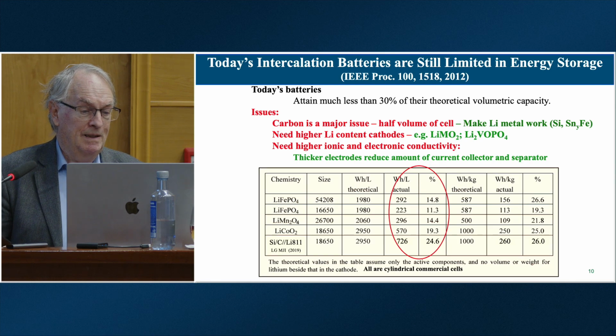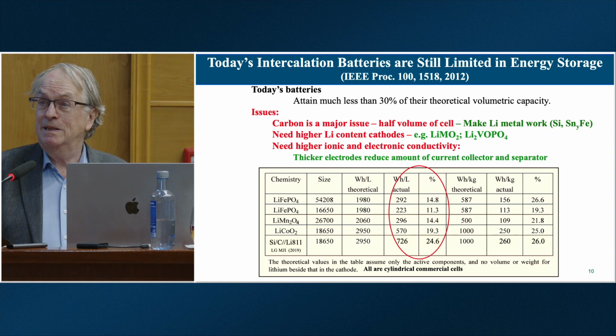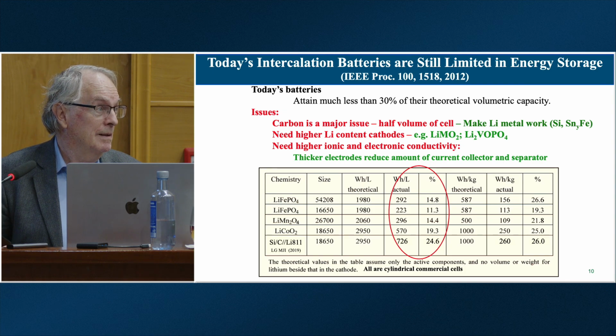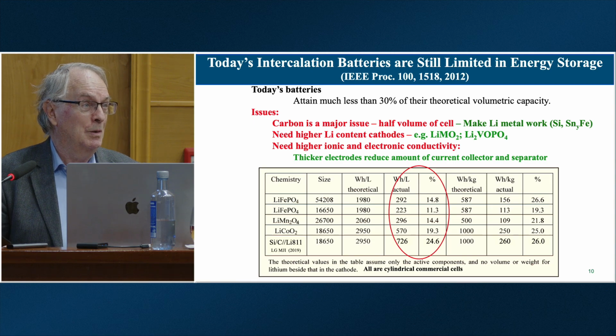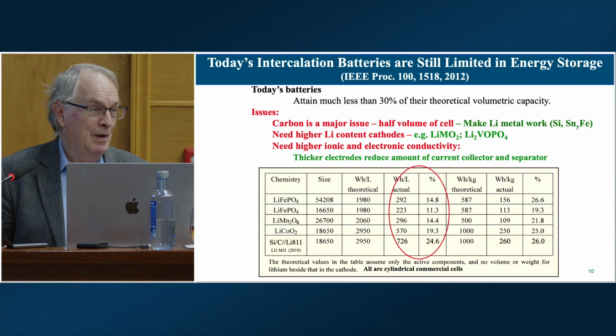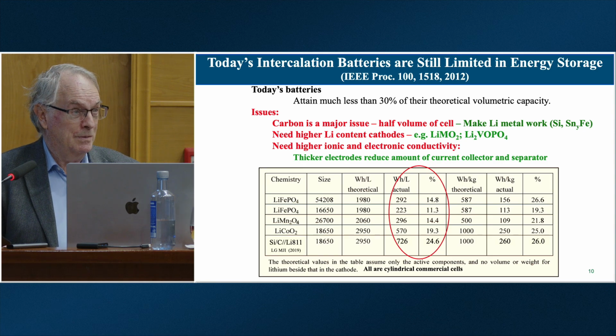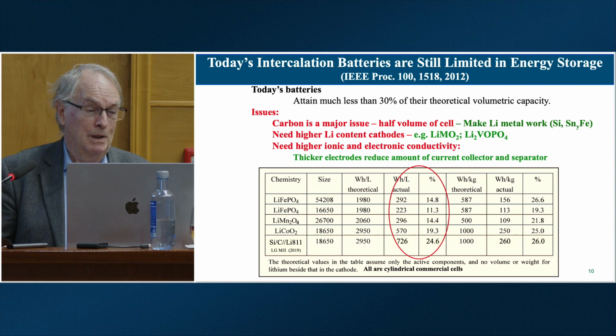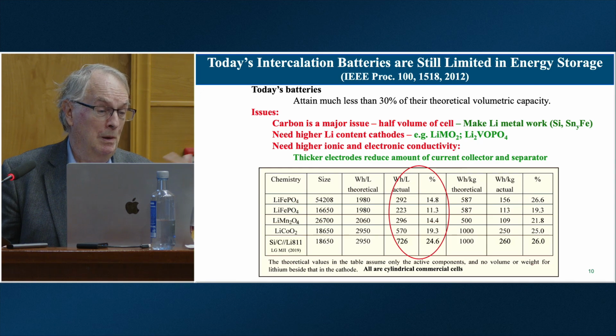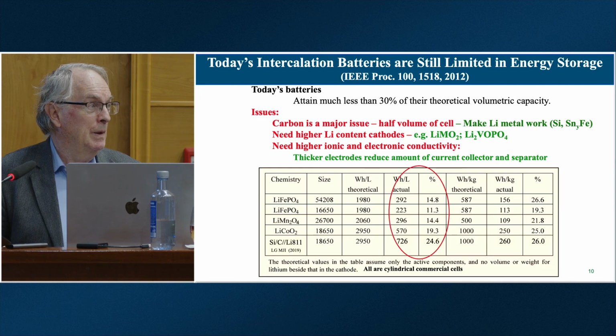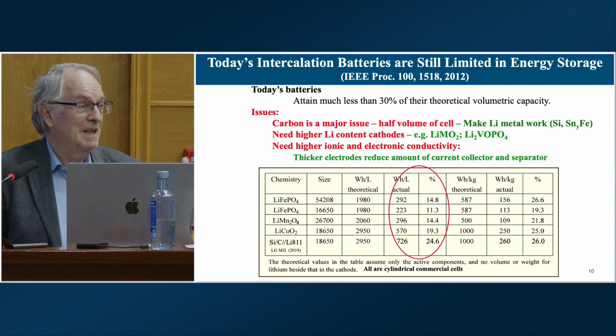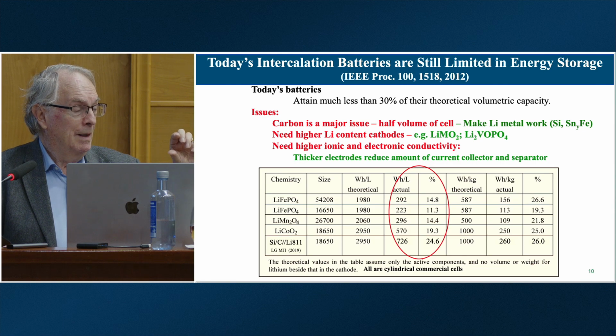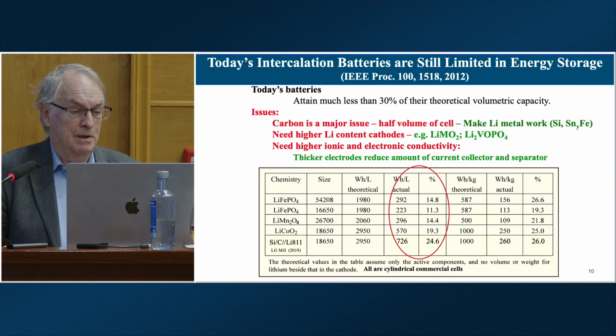On the far right-hand side, you can see if you do it on a weight basis, it's roughly 25%. So there's still a huge opportunity of increasing the stored energy density. But we've got to get rid of that graphite, which I mentioned, which takes up half the volume and much of the weight. And we've got to get more lithium in there. And the other thing we have to do is make those lithium ions move faster in the materials. If we do that, we can make the materials thicker, then we can get rid of more of the dead weight, the separators, the current collectors, and so on.